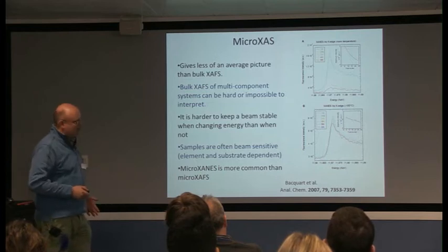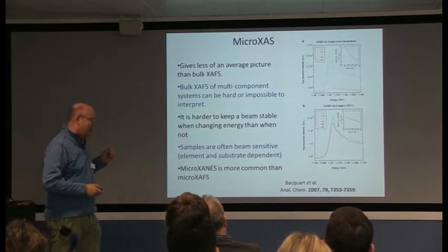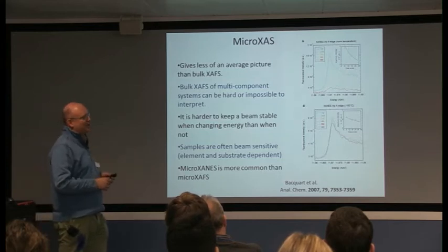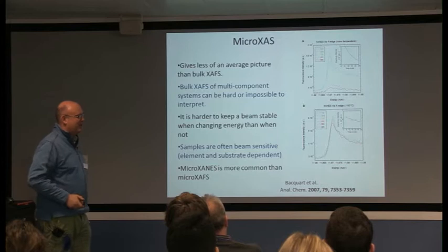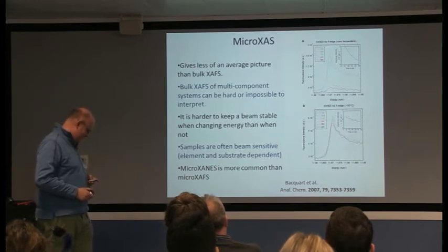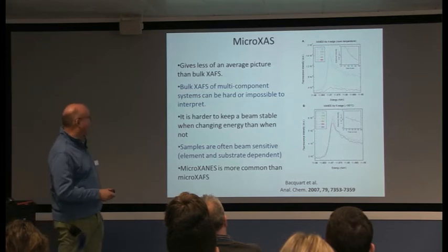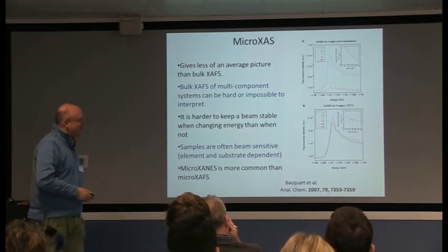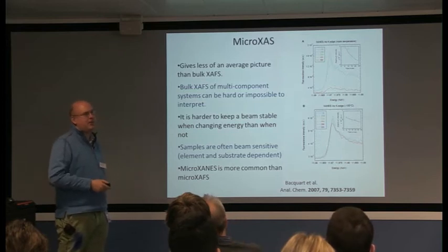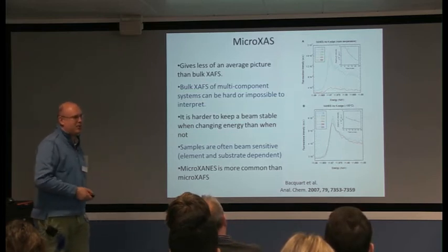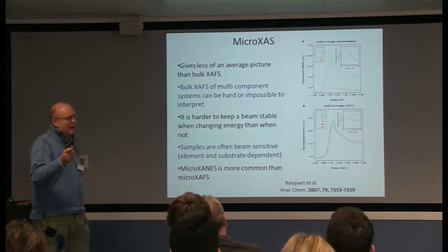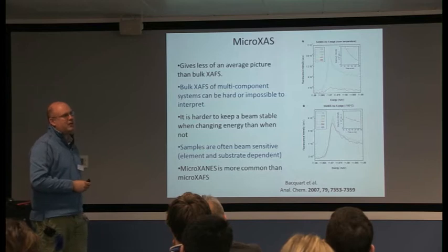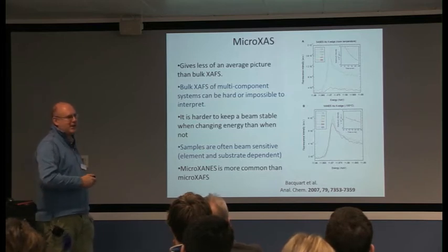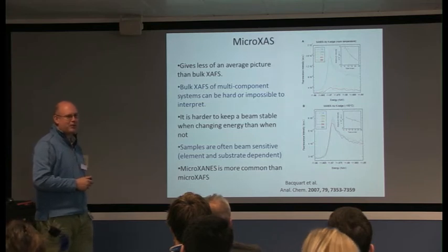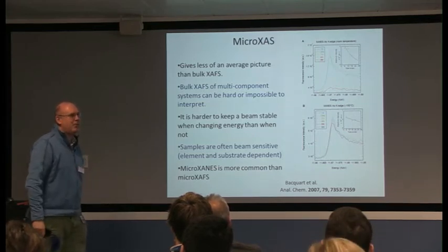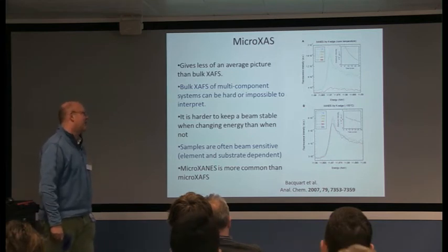But often samples degrade in a beam - I was reviewing a paper only this week which was advocating using big beams rather than small beams, because it said big beams are better at not wrecking your sample, since you've got a much lower photon flux density on the actual bit of the sample. So even though, say, B18 has maybe about 50% less flux than I-18 at our best, its flux density is spread over a millimeter rather than over a 2 micron square, and so the speed your sample will degrade at is generally much slower on B18 compared to I-18.